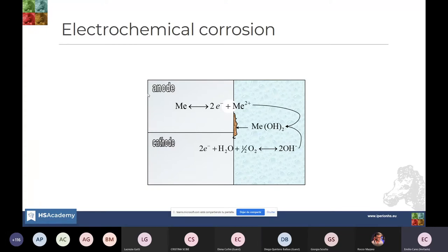That means that these anodic and cathodic reactions taking place on the surface of the metal are taking place within an electrolyte layer. This electrolyte layer can be the water if it is submerged, or can be a layer of adsorbed water that is attached to the surface of the metal in an atmospheric environment. Within this electrolyte layer, we have anodic reactions, which are the oxidation of the metal, and cathodic reactions, mainly the reduction of oxygen, which yield different charged species that react and form the corrosion product.